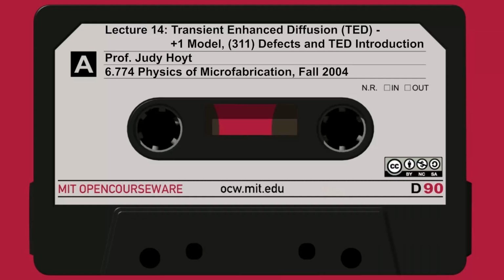The formation energy is roughly 3 electron volts for a silicon interstitial. People have fit data to show that the binding energy of a silicon to this 311 cluster is about 1.8 electron volts. So people have estimates for this term and this term. You can put in estimates for the nearest neighbor distance, and C_I0 can be estimated. So you can plot this equation, C_I max over C_I star, as a function of temperature. And in fact, that's what slide number 16 shows.